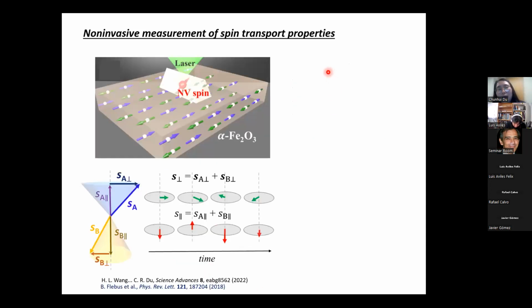So this is our measurement platform. The material is called alpha iron oxide. It is a material system that has been discovered, using spin transport measurement, to have a long spin decay length. And at low temperature, this material is a uniaxial antiferromagnet. So there is no net moment, and the two spin sublattices are antiparallel to each other. In order to measure the spin fluctuation, we transfer a diamond nanobeam containing a single NV center on top of the material surface.